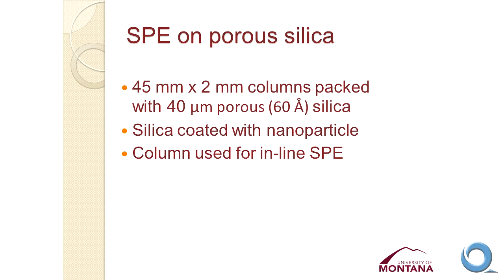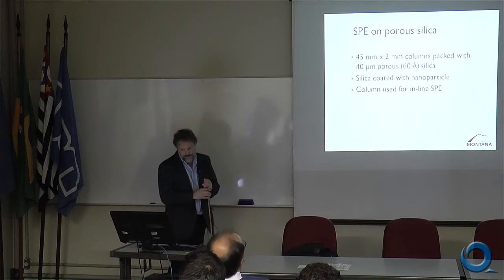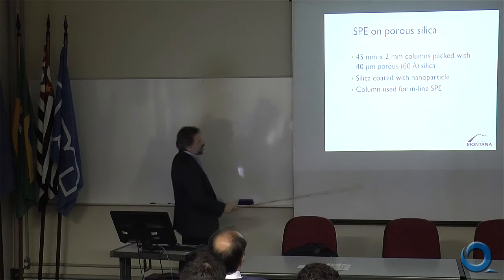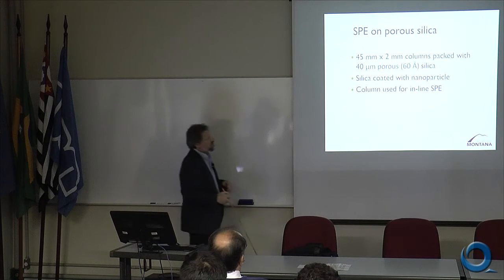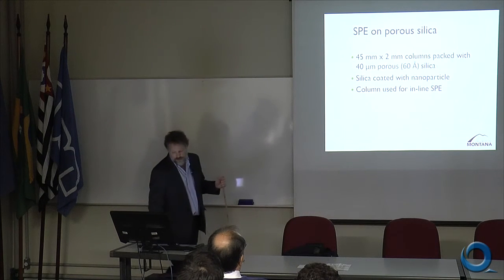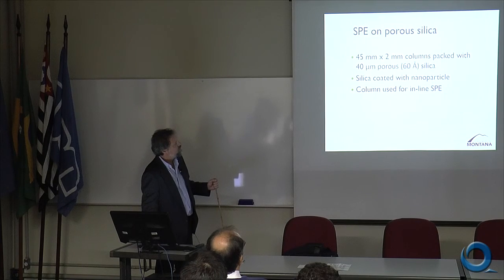So we moved on from there to start to do some solid phase extraction on porous silicas. And so the idea is to increase the surface area available, change that phase ratio, and get to a point where we can really start to measure the interactions of our solutes with the nanoparticles coated on the silica particles. And so we set up an inline solid phase extraction system where we could do a series of experiments to measure these interactions.